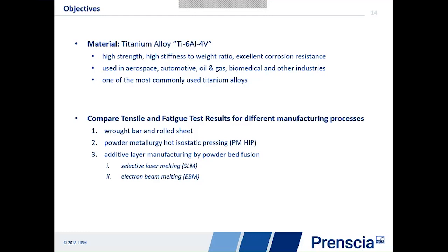What we're going to do is compare the tensile and fatigue test results, and look at different manufacturing processes with the same material. We're going to start off with wrought bar and rolled sheet as our background level, so we can assess additive manufacturing powder metal in comparison to those. We're then going to look at powder metallurgy, hot isostatic pressing as a method, and look at how that compares to the wrought bars. And then we're going to look at two methods of additive layer manufacturing using powder bed fusion. In particular, we're going to look at selective laser melting and also electron beam melting.